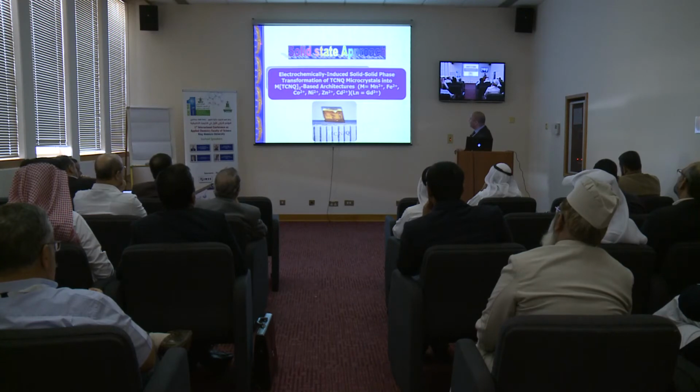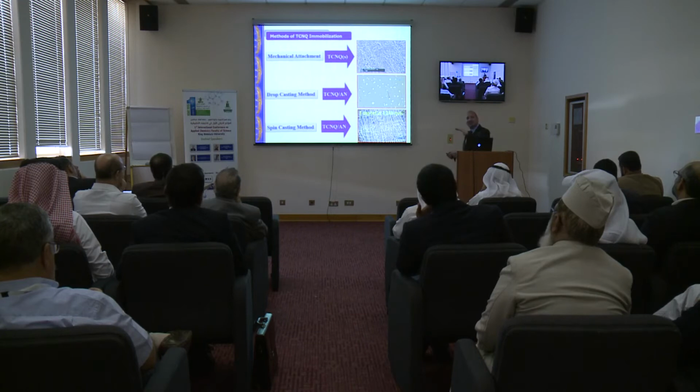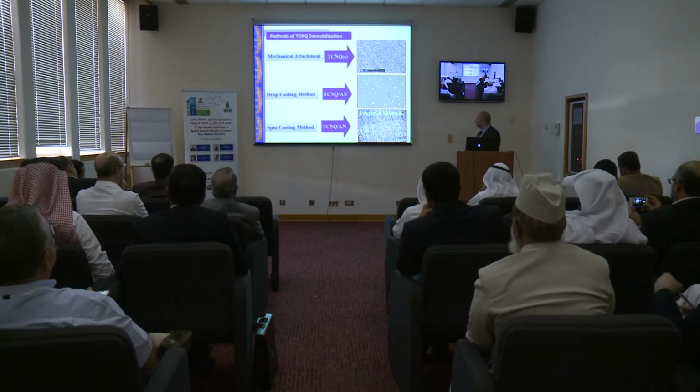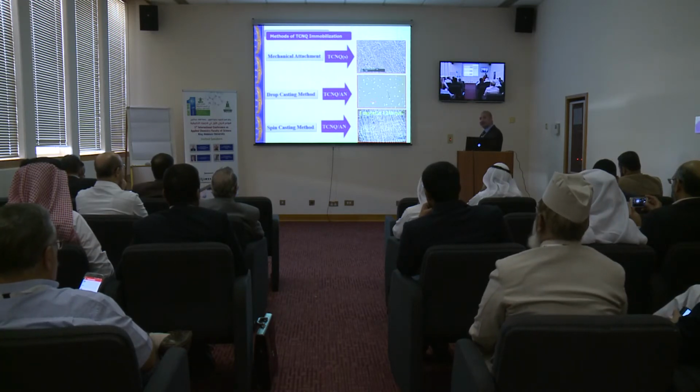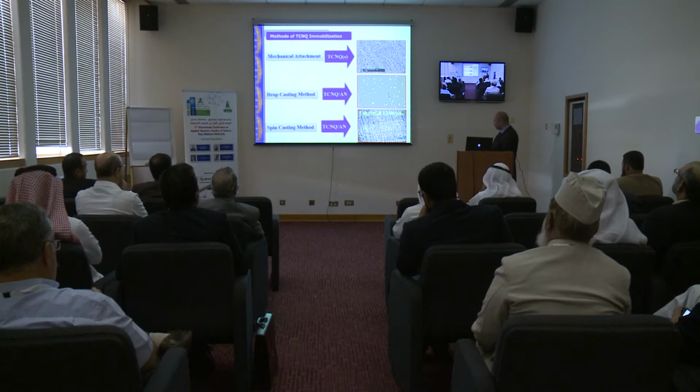The second approach, which is very simple, we can do a lot of work on this. So basically, we start with TCNQ. We just modify any glass conductive substrate like indium tin oxide by the solid of TCNQ, we're getting this amorphous structure. You can also get the TCNQ dissolved in acetonitrile and drop cast it to the electrode surface. You're getting this kind of morphology, as well as if you start with spin coating. So spin coating, you can get different types of starting material.